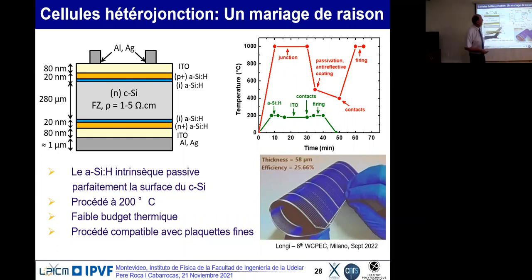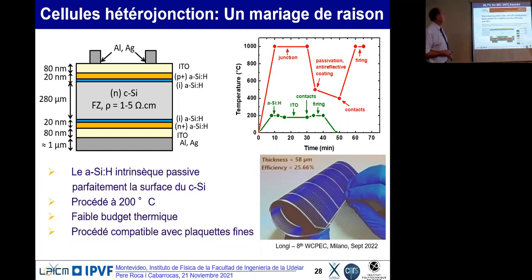For the PN junction, you need a high temperature process. And if you have a high temperature process with aluminum, the difference in thermal expansion coefficient makes the cells break if the wafers are thin. Using a low temperature process for the silicon passivation layers allows you to work with thin wafers, which you can bend. So you reduce the material, you make it flexible, and that's one of the next generation of crystalline silicon solar cells.